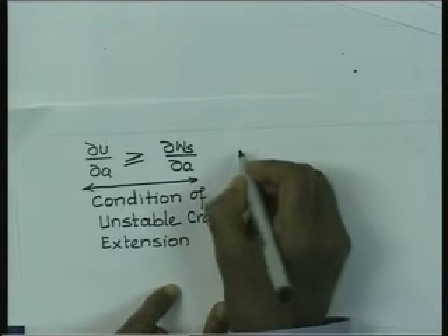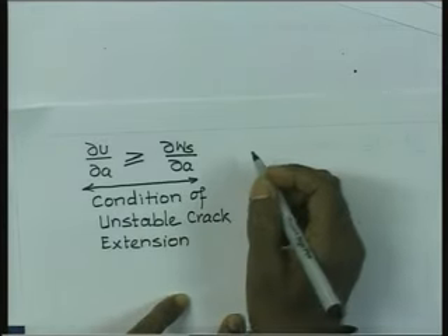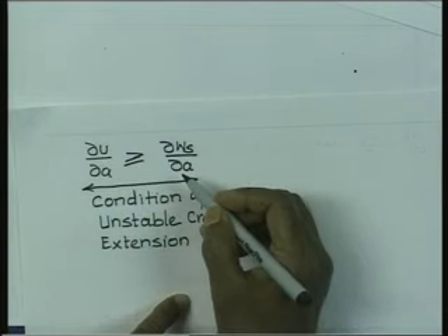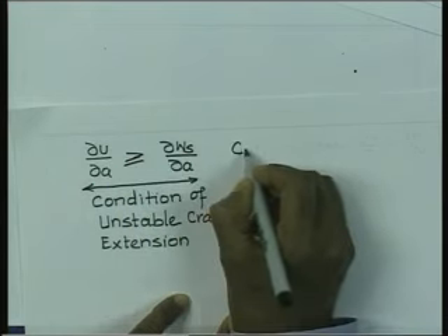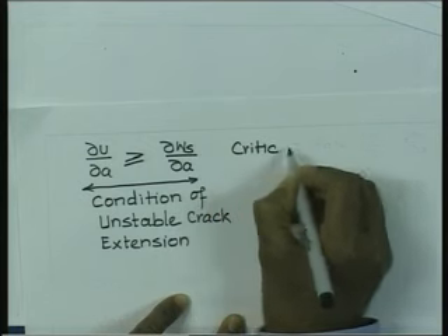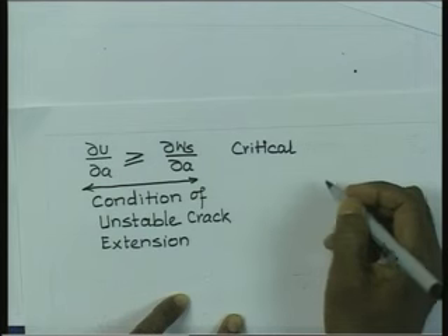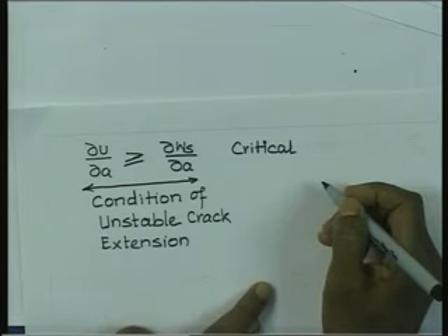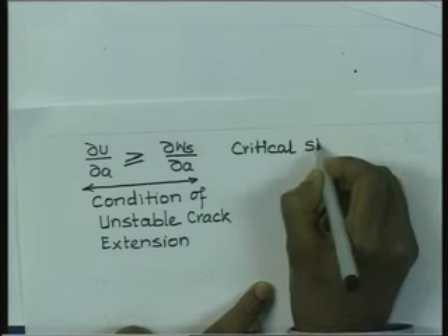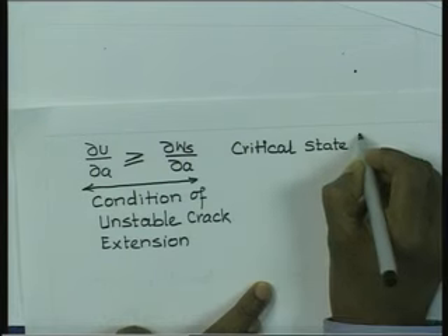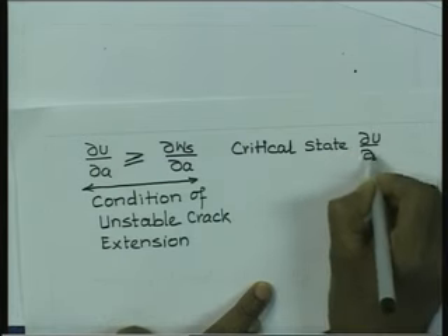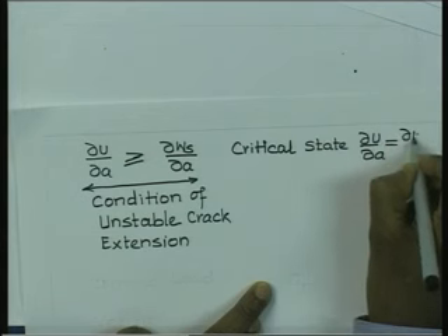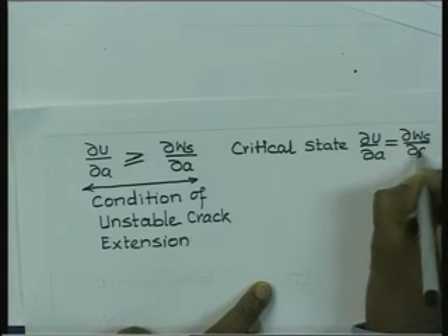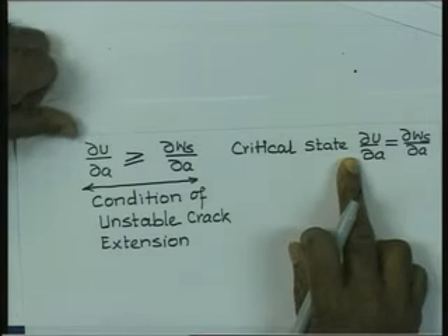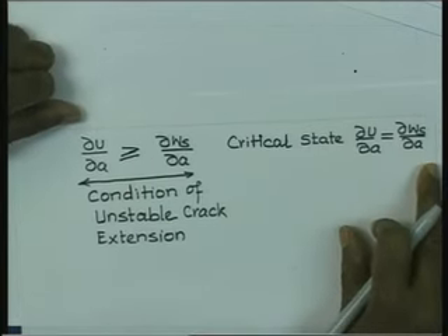So, the critical state is reached when delta U by delta A is equal to delta Ws by delta A. So, the critical condition when the crack is going to begin to extend is given by this condition, delta U by delta A is equal to delta Ws by delta A. So, the crack is going to extend when delta U by delta A is equal to delta Ws by delta A.